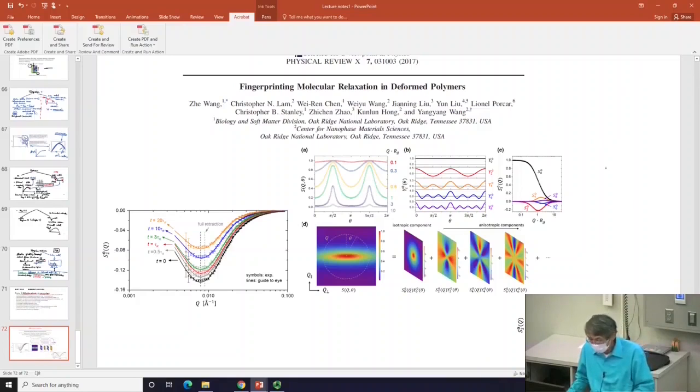What was carried out was stretching a piece of polystyrene by a factor of 1.8 lambda, so nearly twice, but not there yet. So it's below the finite extensibility limit. So when you extend, the sample doesn't break. It sits there stationarily. And then he's going to watch whether the chain retraction occurred or not. If it occurs, it has certain features. If it doesn't, it has certain features.